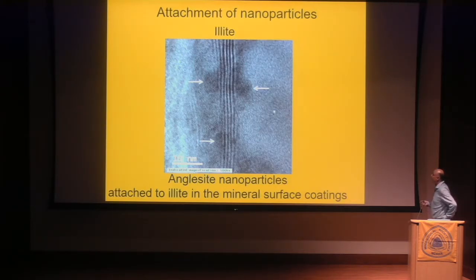Here is a really impressive image. We have here an illite crystal in the mineral surface coating, and you can see here that those anglesite nanoparticles attached to the basal surface of the illite. Here nicely shown are the sheet structures. So you have not only agglomeration and aggregation processes, but also attachment of nanoparticles to silicate surfaces.